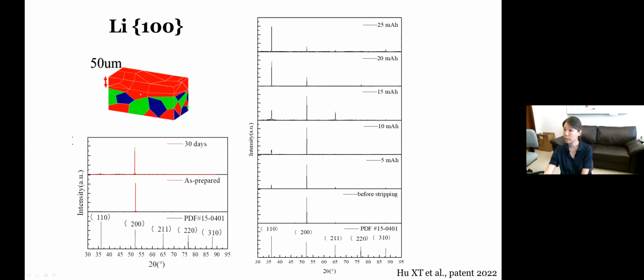Right. To estimate the thickness of such a surface texturing layer, we did a stripping experiment. So the samples are stripped at different capacities at the current density of 1 milliamp per centimeter square, and 1 milliamp hour capacity corresponds to about 5 micron thickness of the lithium in the current experimental setting. So what we show is that we consider a specific crystallographic orientation of HKL. In this case, it's the 100 as the dominant one, when all the other diffraction intensities take less than 20% of the total. Right, so up to here, we still have very good dominance of the lithium 100.